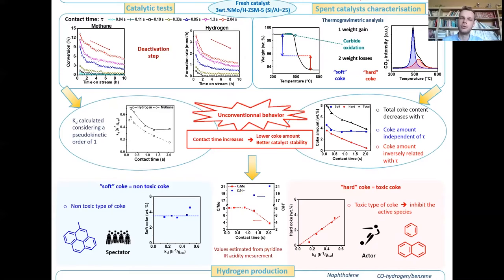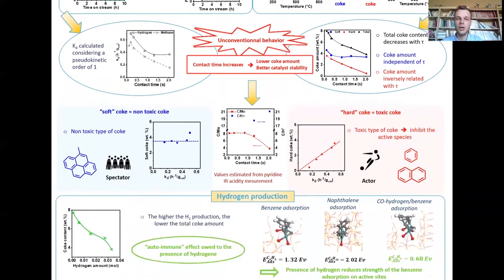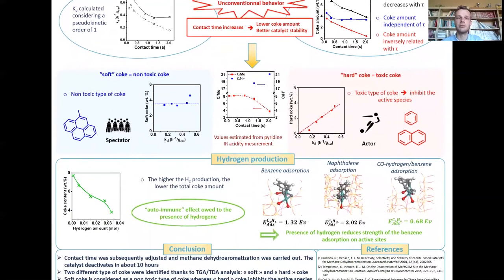Indeed, as the contact time increases, we lower the coke amount and we have better catalyst stability. So we decided to distinguish these two types of coke.